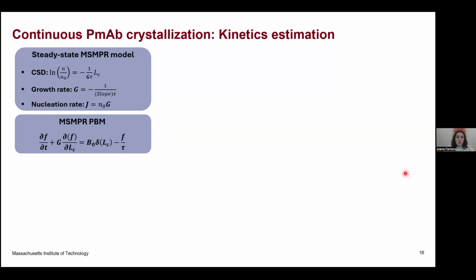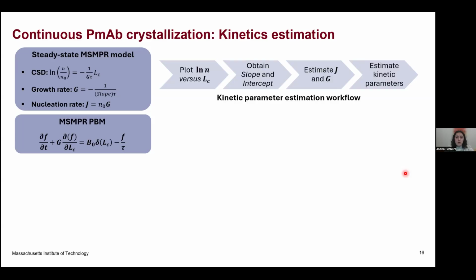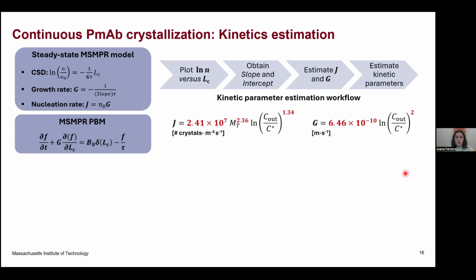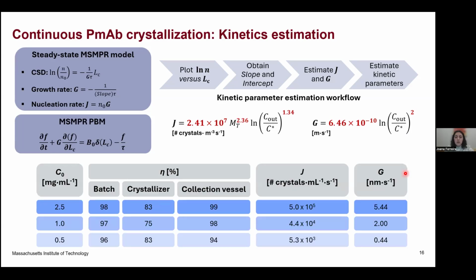And then, so if you still remember, we had the 3 different steps: screening, solubility, and kinetics. This is the last step. So we are trying to combine the steady state MSMPR model with the population balance modeling. So with this approach, we can estimate nucleation and growth rates. Also from the population balance modeling, we can come up with an expression for these 2 different variables that are very important to quantify, especially nucleation rates.